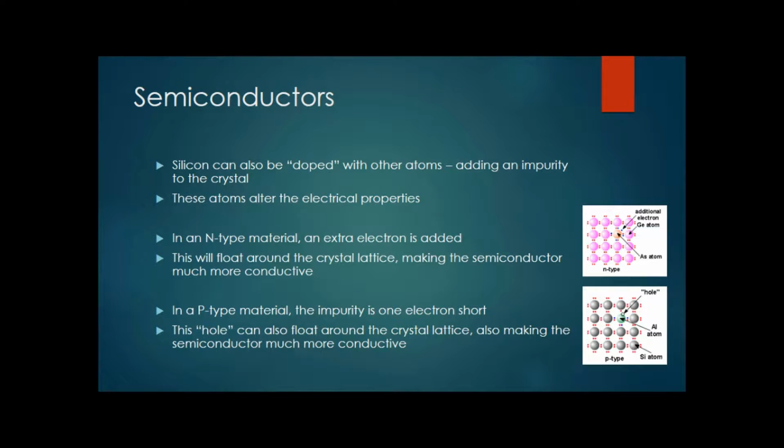Now, silicon is a very interesting substance because it's what's called a semiconductor. And you can play with its electrical properties very simply by adding little bits of contaminants in there, basically, a different atom. So in this case, this is a germanium crystal with an atom of arsenic stuck in there every so often. And arsenic's a very similar material to germanium, but has a different number of electrons. And so what this does is it has an extra leftover electron, and it actually can roam around in the crystal, the same way electrons will roam around inside of a metal. So it makes the material suddenly change from a very good insulator into a pretty good conductor.